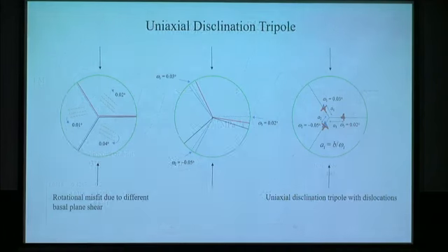So the idea is, how do we handle this plastic strain incompatibility? For example, between this crystal and this crystal having different orientations, this one tries to rotate or shear by something like 0.02 degree, and this one shears this way, and this one shears this way. It's something like a misfit between this crystal and this crystal, and we can perhaps model this in terms of a disclination. A disclination is a rotational equivalent of a dislocation, and these disclinations can generate significant stress concentrations. If I use this model, I will come up with a disclination dipole, one here and one here.